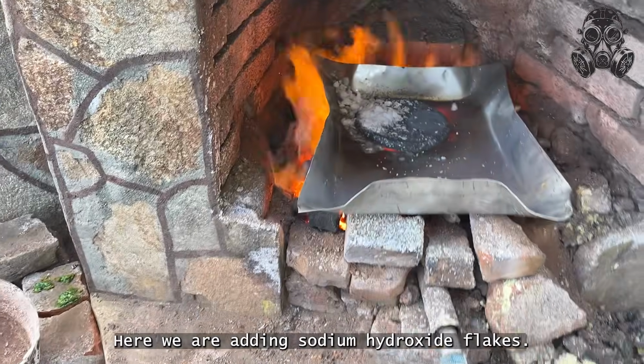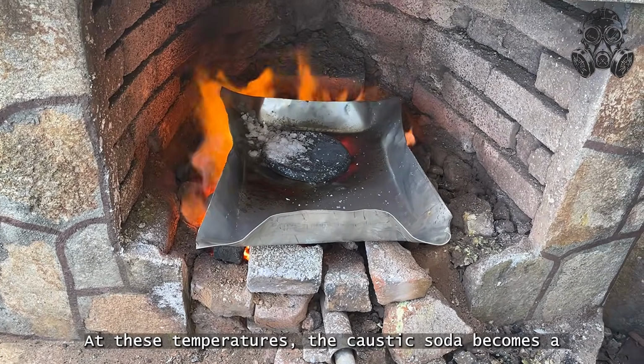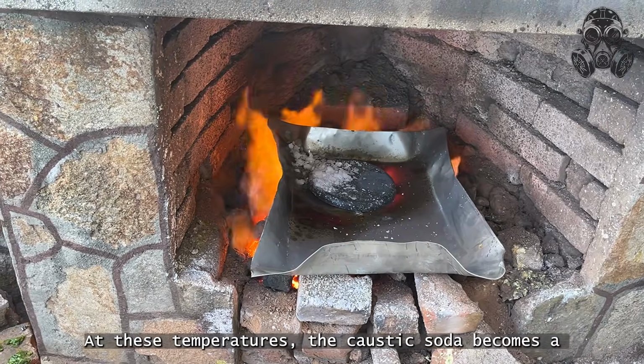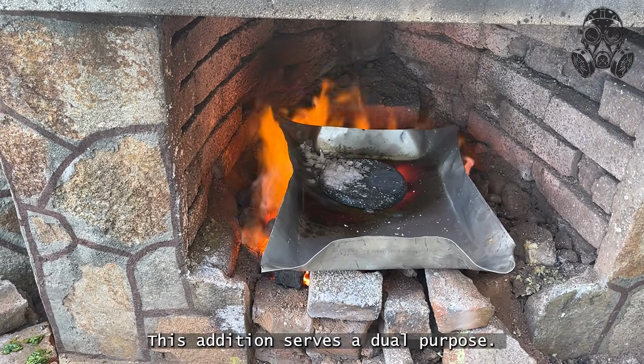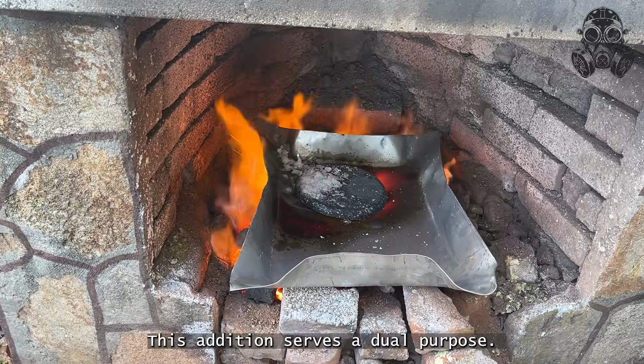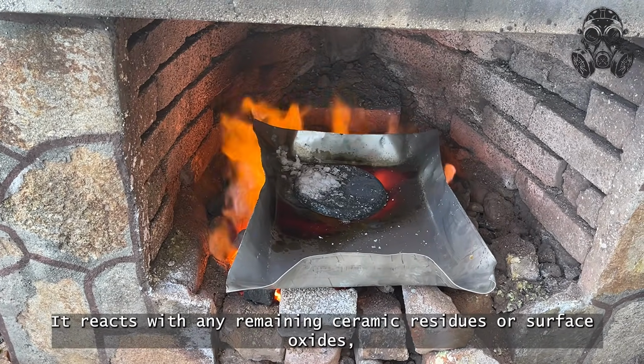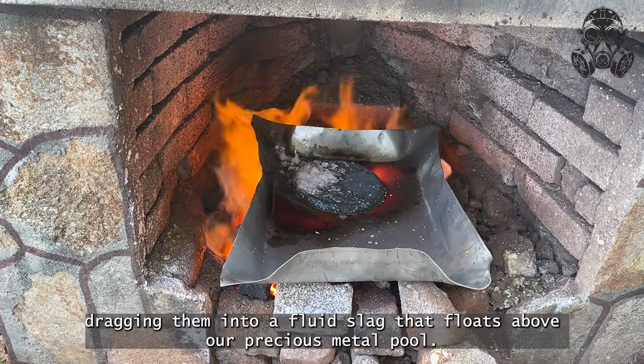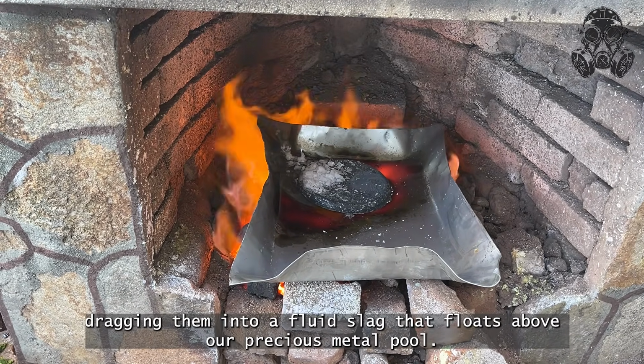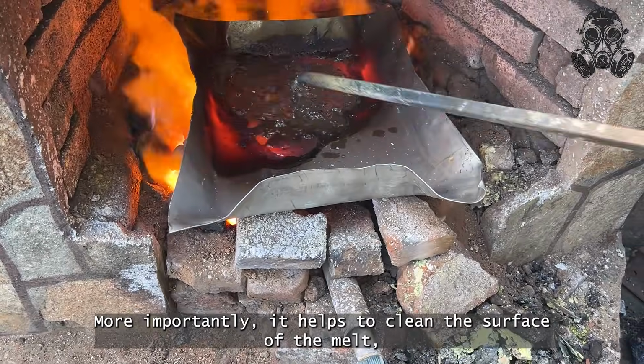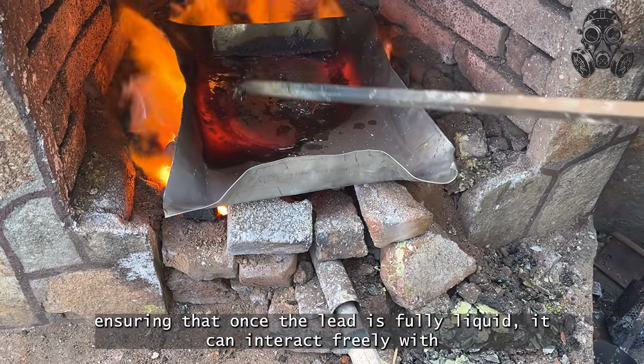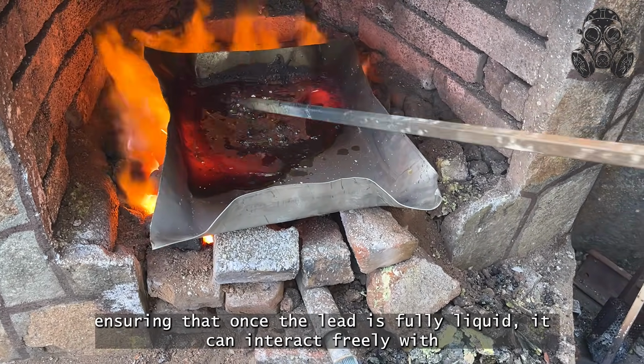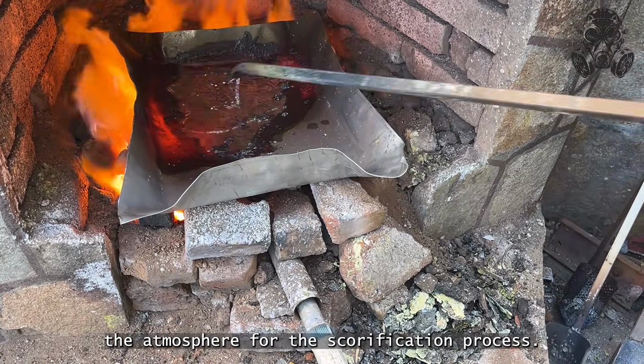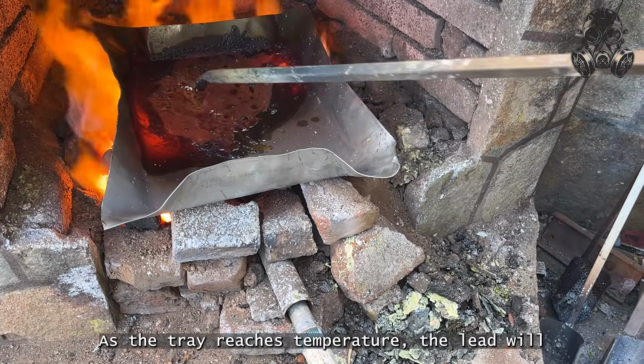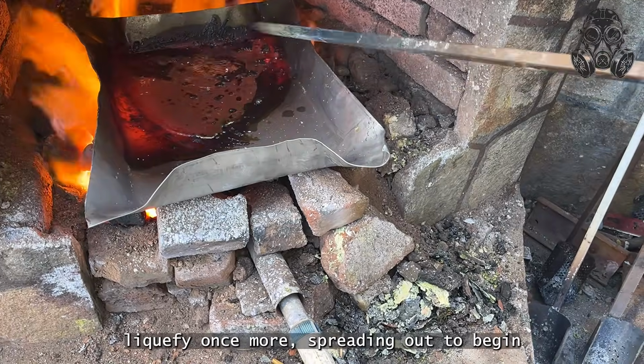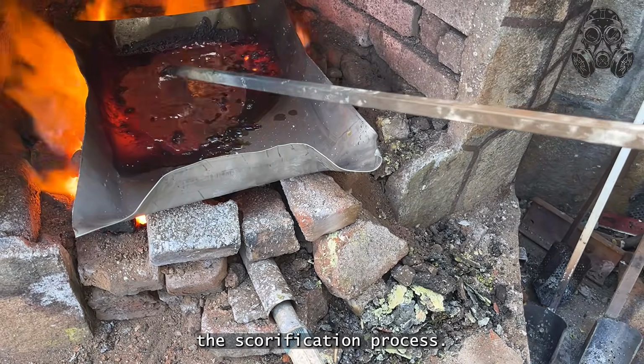Here we are adding sodium hydroxide flakes. At these temperatures, the caustic soda becomes a highly reactive liquid flux. This addition serves a dual purpose. It reacts with any remaining ceramic residues or surface oxides, dragging them into a fluid slag that floats above our precious metal pool. More importantly, it helps to clean the surface of the melt, ensuring that once the lead is fully liquid, it can interact freely with the atmosphere for the scorification process. As the tray reaches temperature, the lead will liquefy once more, spreading out to begin the scorification process.